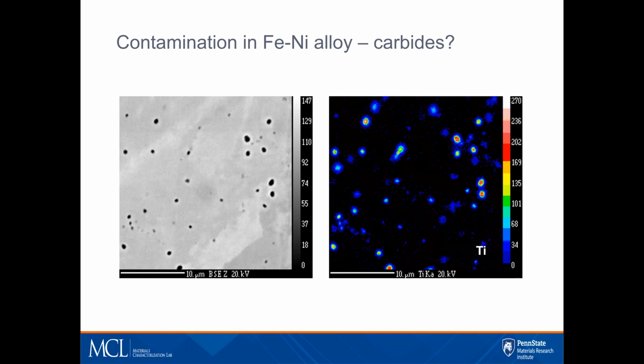Turns out that they're contaminants of titanium. And so looking back at it, this is an additive material, and it turns out that the user prior to this particular material had used titanium in their process and had not cleaned the nozzles properly. And so little particles of titanium got trapped in this material. So they were able to clean out the titanium and then reprocess and eliminate those specks.